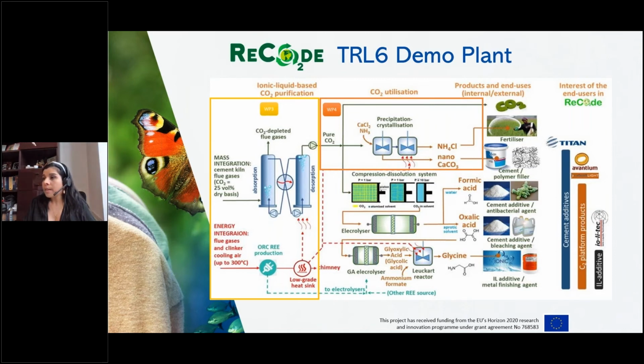A first part is related to work package 4 of our project, related to the precipitation and crystallization of this CO2 together with a source of nitrogen in order to produce nano calcium carbonate and ammonium chloride. And then we have 3 different routes of electrocatalytic and catalytic processes that will exploit the CO2 for the production of useful value-added products like formic acid, oxalic acid, and glyoxylic acid, and later glycine.